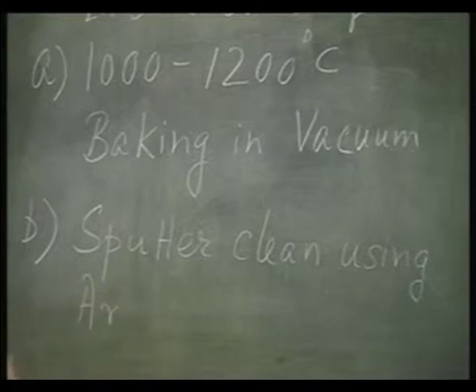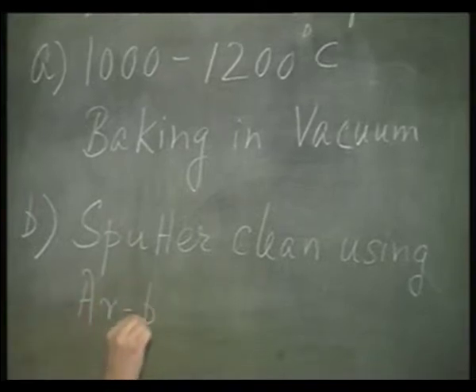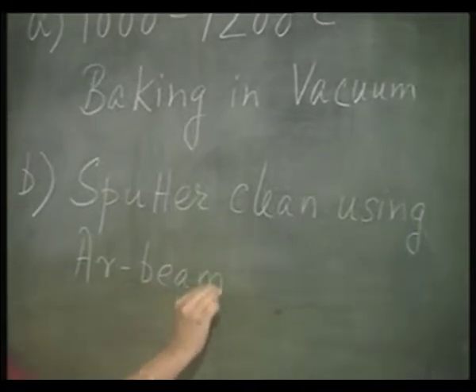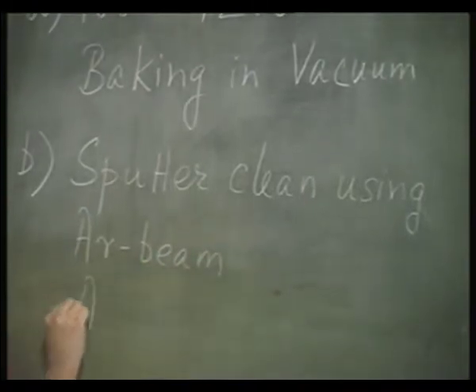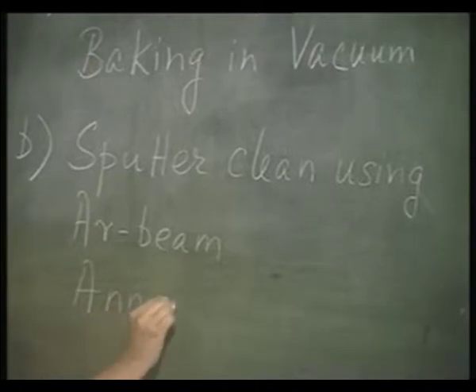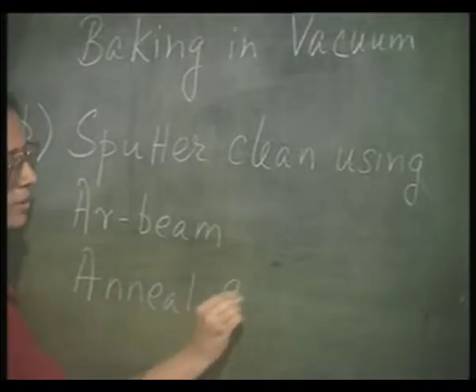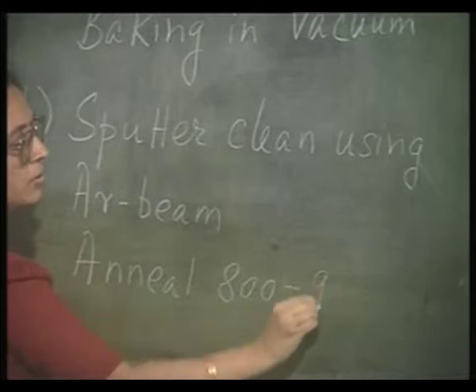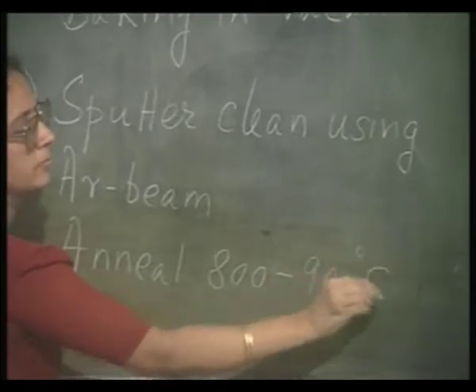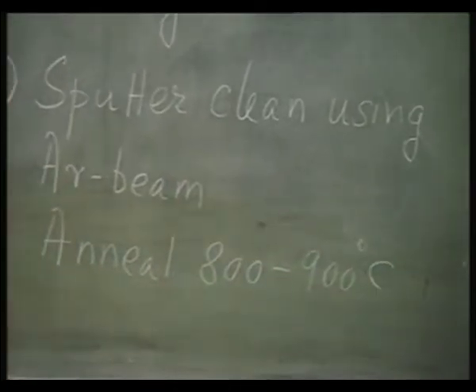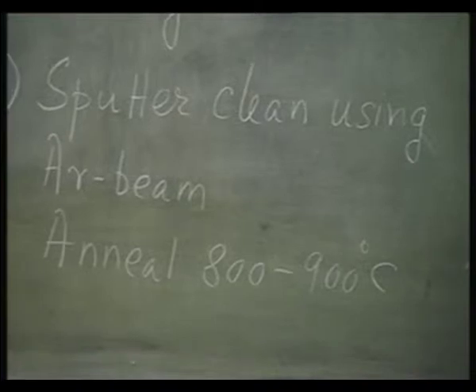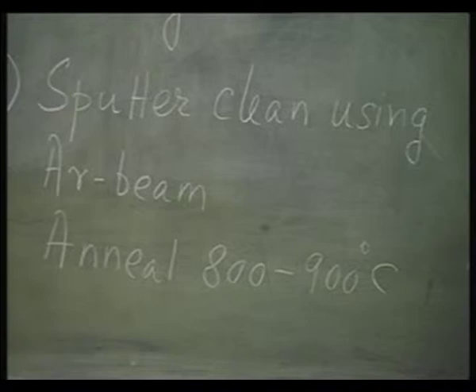Normally, argon beam is used. Argon is an inert gas, as you know. This has to be annealed at 800 to 900 degrees centigrade in order to clean the surface of the damages in addition to the sputter cleaning. Okay.